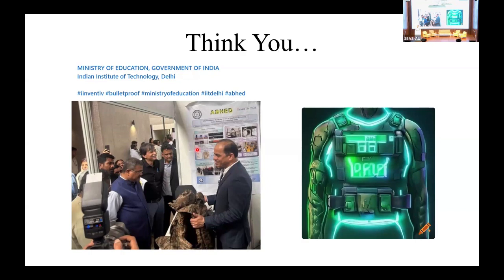Anything else? You have mentioned that when a bullet hits the ceramic panel, it will crack suddenly from that point. Yeah, radial and circumferential. Have you done any damage mechanics or fracture mechanics study of how that propagates and how it will damage the system? We did try it, and we have a camera which has a speed of 10 lakh frames per second, and we found that 10 lakh is too small a number. Oh, sorry, 1 lakh. 1 lakh frames per second is a small number. We require more than 3 lakh frames per second to track or to measure the speed of growth of a crack in a piece of glass.